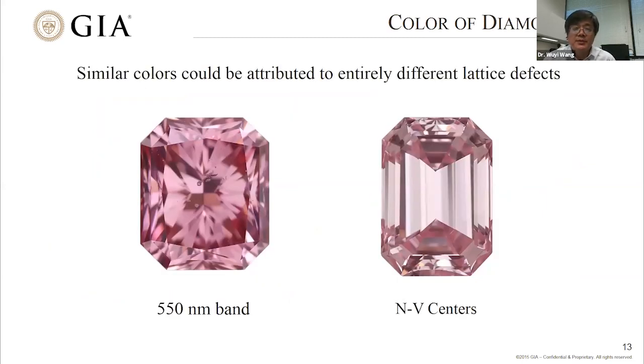One more thing I want to talk about regarding the color of a diamond is similar color. For example, I show here two pink diamonds. Both are pink, and similar color could be attributed to different defects. Diamond could have many types of defects. The stone on the left, actually a pink diamond from the Argyle diamond mine, is colored by a defect we call the 550 nanometer band. Argyle pink diamond is exclusively due to this 550 band defect, which gives the pink color. But the stone on the right-hand side is a similar color, but it's due to NV centers. So the concept is a similar color of a diamond could be attributed to different defects. That is very true for yellow diamonds. There are many, probably close to 10 types of defects that could introduce yellow color or orange color in a diamond.